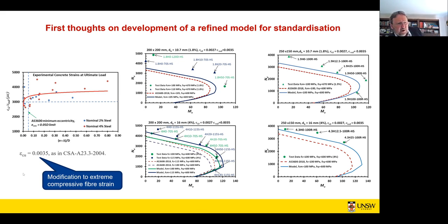And 0.003 is not a bad lower bound predictor, but it's a fairly poor mean predictor. And if we look at everything and we always err on the conservative, those conservative errors add up and we end up with a conservative model. The Canadians look at means and then they make the adjustments at the reliability level. And that's the approach which is much more sensible. And they have a strain of 0.0035. And if you look at 0.0035, it's a much better value of the average.